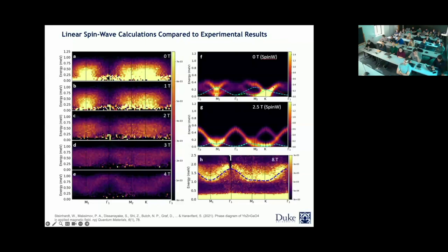And by doing that, we were able to look at the inelastic neutron scattering. Here you're looking at the energy versus Q. And again, we started to look at different fields, 0, 1, 2, 3, and 4, and also we went up to 8 Tesla. We were able to see what looks like a continuum of excitations. You can see that it's very diffuse, and even in the case of 8 Tesla, you can see that it is rather diffuse.